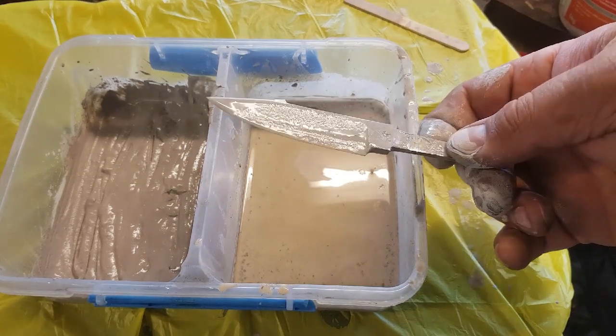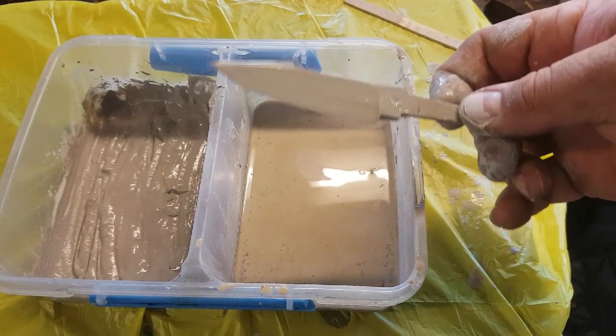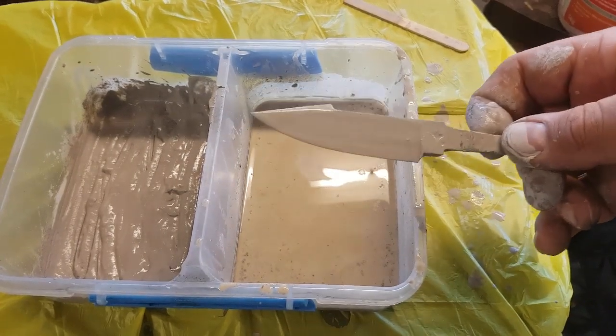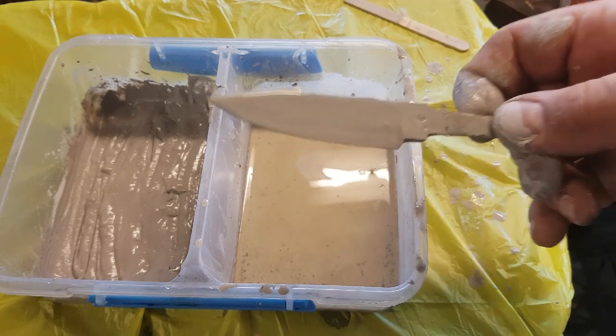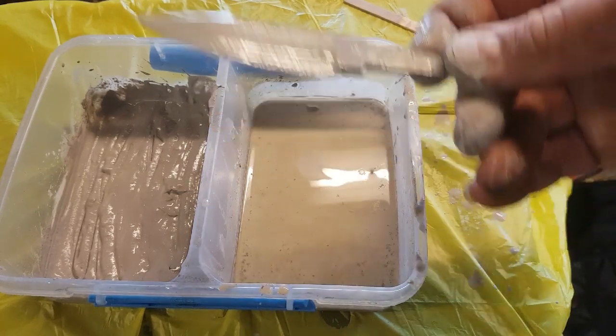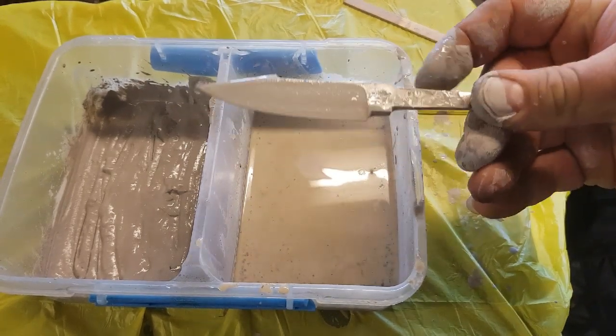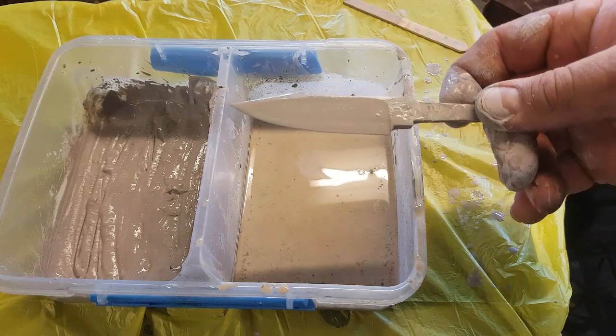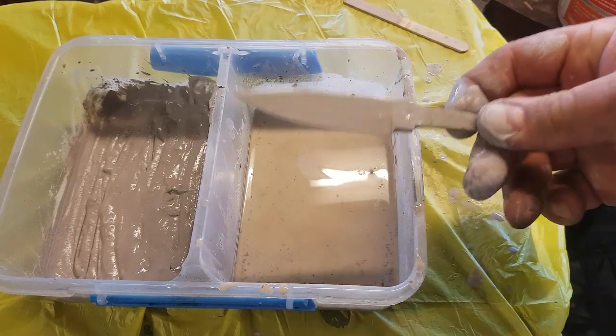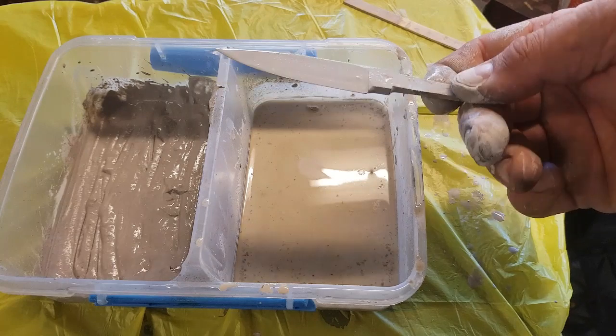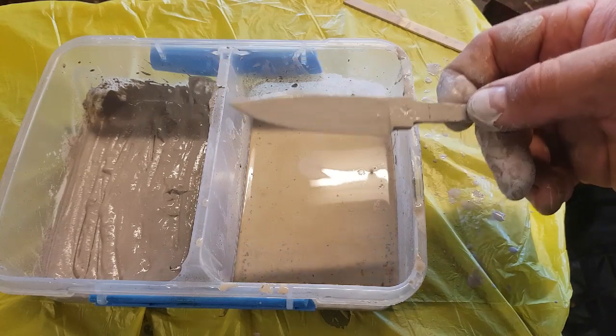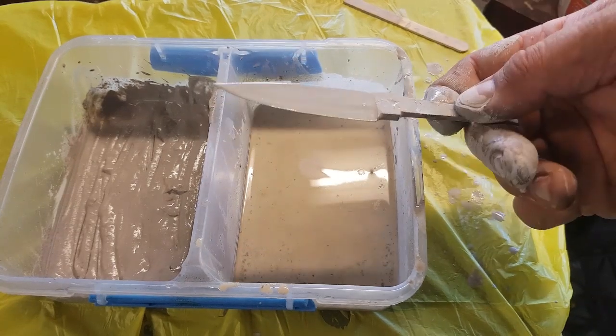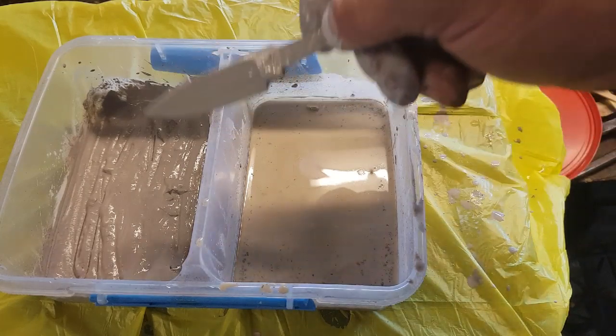So once this dries to the point that it's tacky, I can then hit it with a torch very, very lightly. I'm not even going to touch it with the flame. I'm just going to heat it up. A heat gun would work really well. Or if you hang it over your charcoal forge or your gas forge, then you don't want anything to contact it because you don't want to ruin that layer of clay. But you want it to dry out almost completely. It doesn't have to be 100% dry, but you want it to be fairly dry before you apply the layer of Hamon clay.